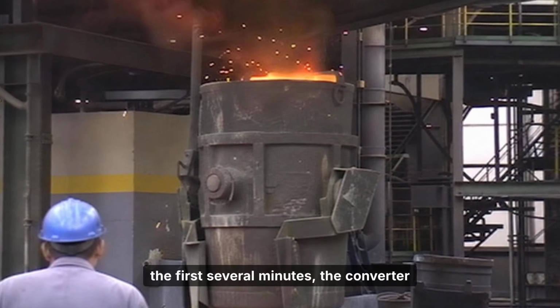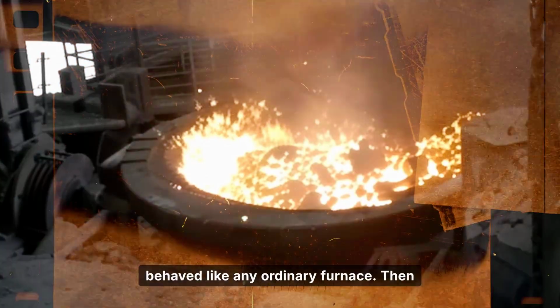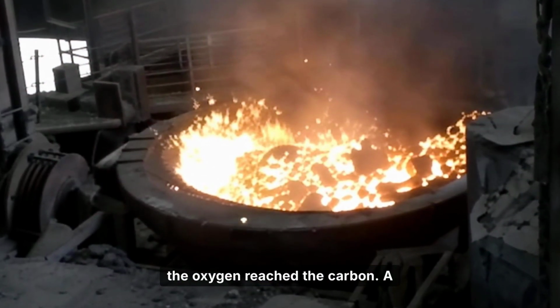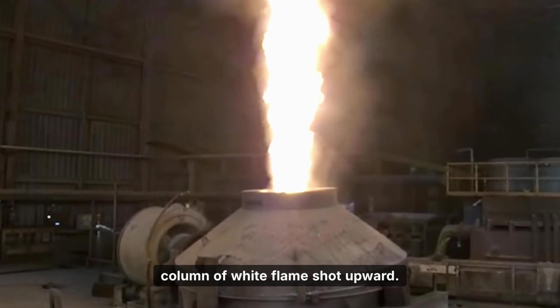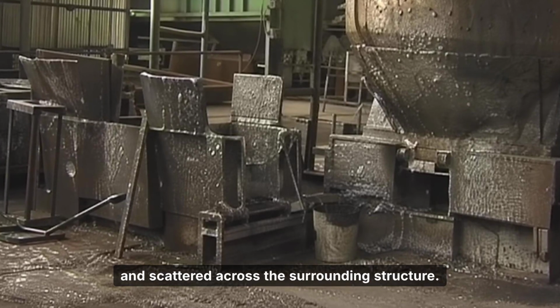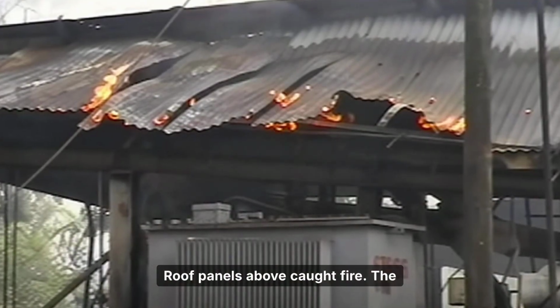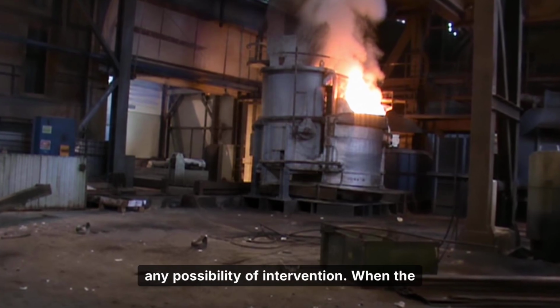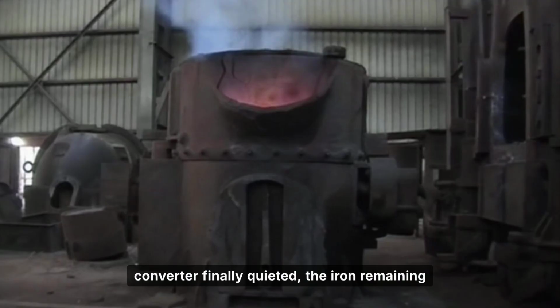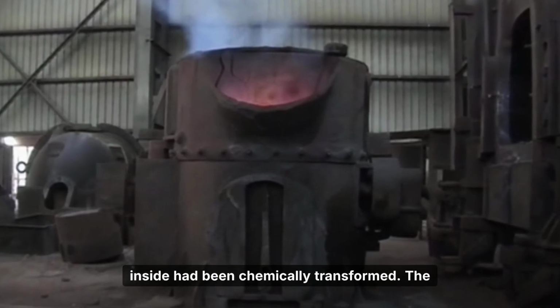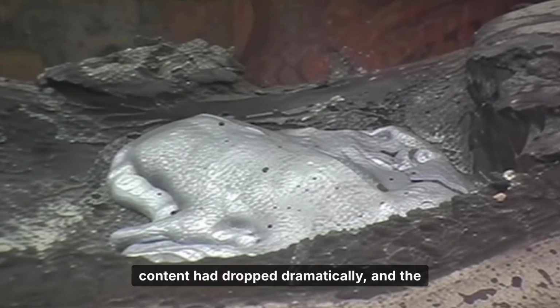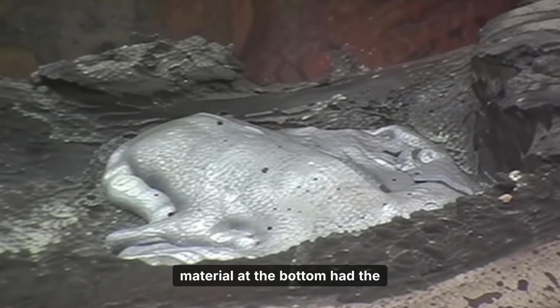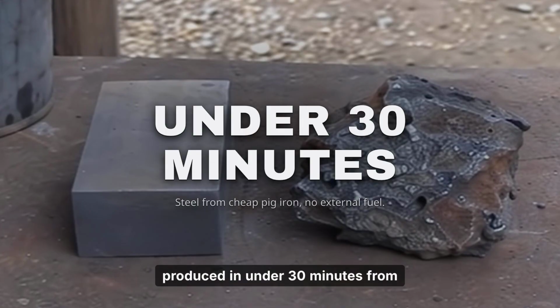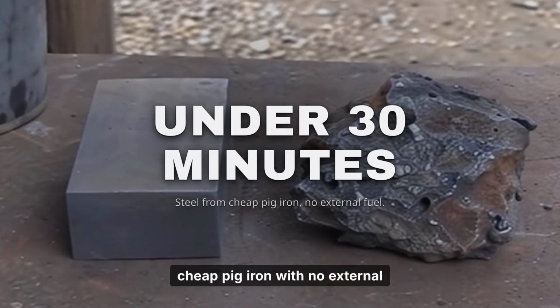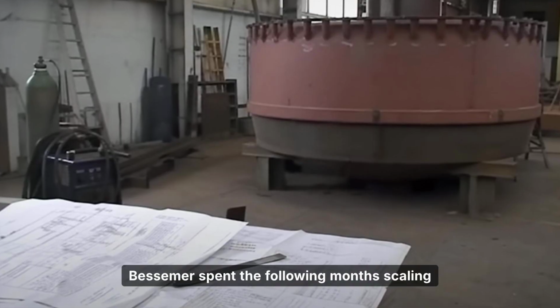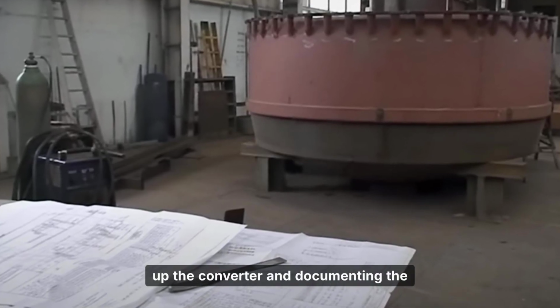For the first several minutes, the converter behaved like any ordinary furnace. Then the silicon burned off entirely, and the oxygen reached the carbon. A column of white flame shot upward. Molten material erupted through the opening and scattered across the surrounding structure. Roof panels above caught fire. The reactions continued for several minutes without any possibility of intervention. When the converter finally quieted, the iron remaining inside had been chemically transformed. The impurities had burned off, the carbon content had dropped dramatically, and the material at the bottom had the composition and physical properties of steel, produced in under 30 minutes from cheap pig iron with no external fuel beyond the initial melting. Bessemer spent the following months scaling up the converter and documenting the process carefully.